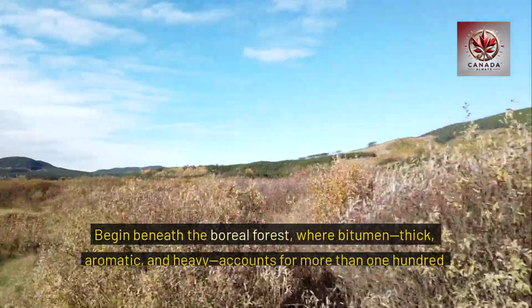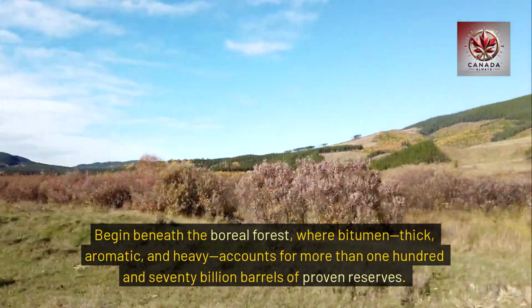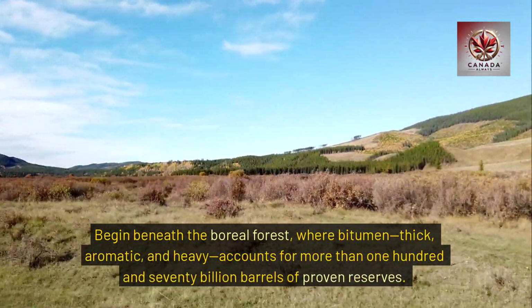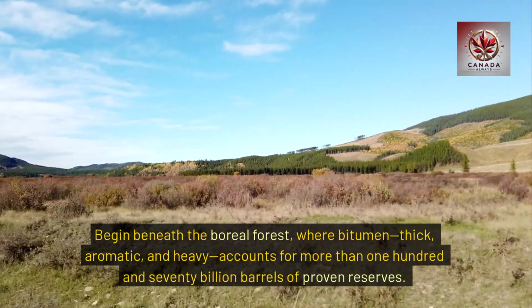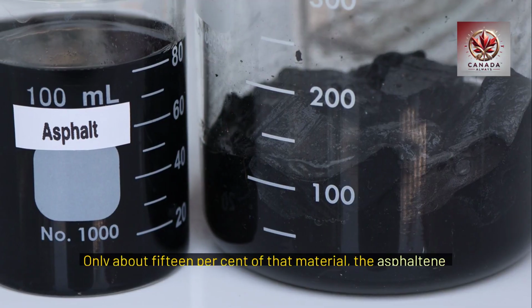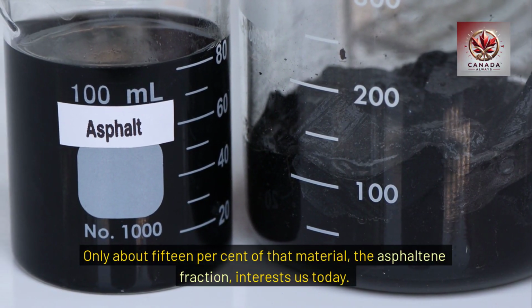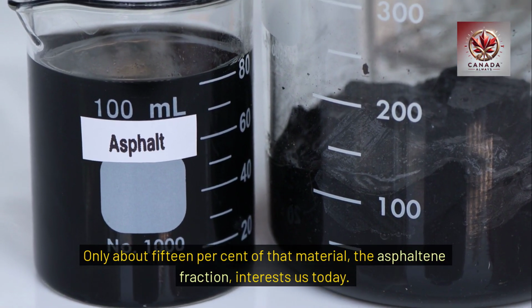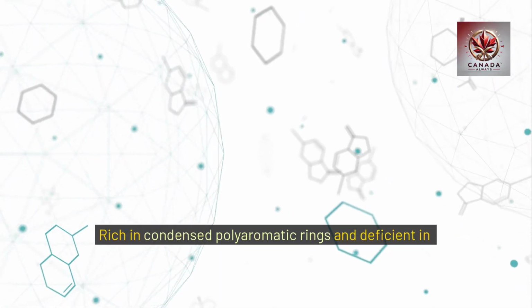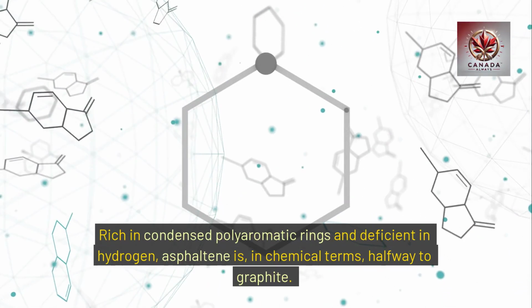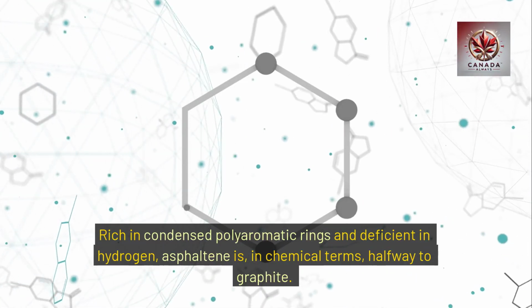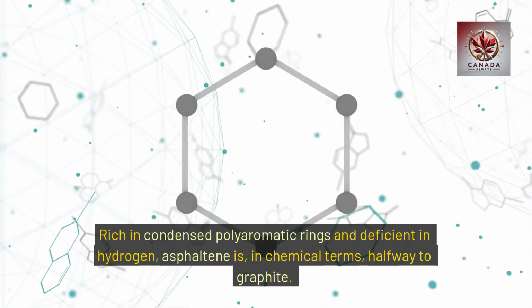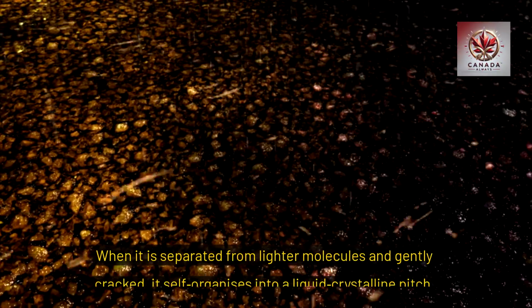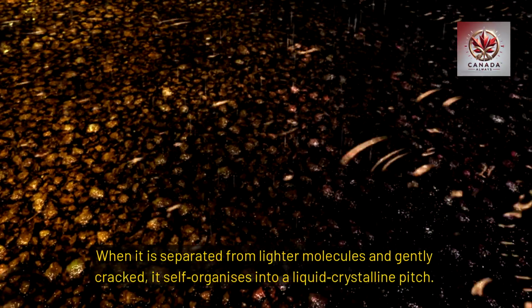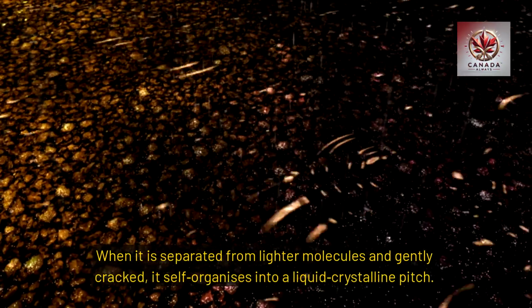Begin beneath the boreal forest, where bitumen, thick, aromatic, and heavy, accounts for more than 170 billion barrels of proven reserves. Only about 15% of that material, the asphaltene fraction, interests us today. Rich in condensed polyaromatic rings and deficient in hydrogen, asphaltene is, in chemical terms, halfway to graphite. When it is separated from lighter molecules and gently cracked, it self-organizes into a liquid crystalline pitch.